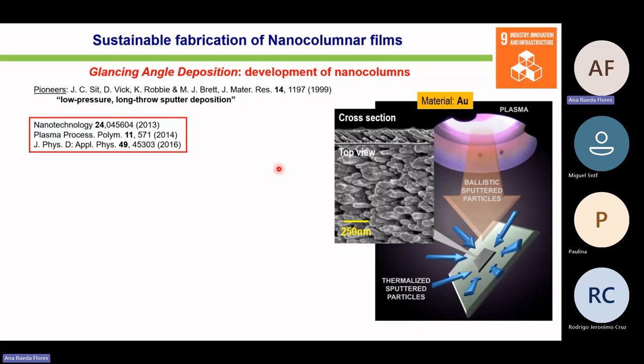What we have to do is we need to tilt a lot the substrate with respect to the target. So we work in glancing angle deposition, and by so doing, we are favoring self-atomic shadowing mechanisms that I will explain in a minute. And as a result, you can see that we have tilted nanocolumns. This is a top view image. This is a cross-section SEM image. So you can see the scale is 250 nanometers. So the typical diameter is tens of nanometers, 30, 40, 50 nanometers. And we can only control that within a certain range, because it depends on many self-control mechanisms that I will explain briefly. However, we can control easily the length of the nanocolumns with the deposition time.